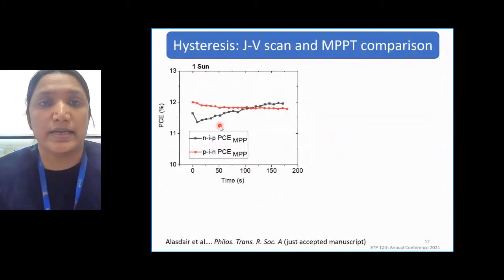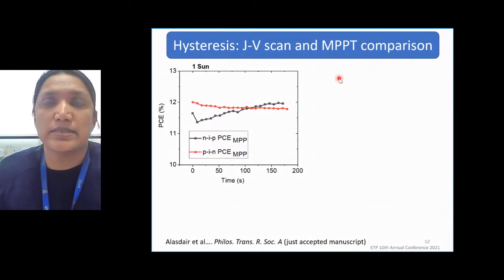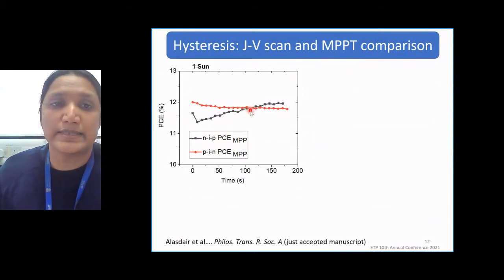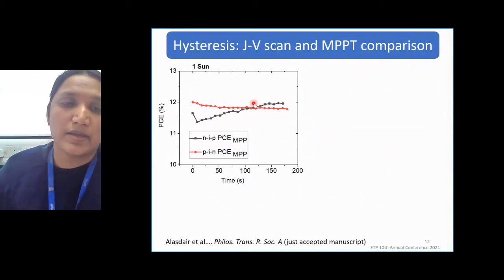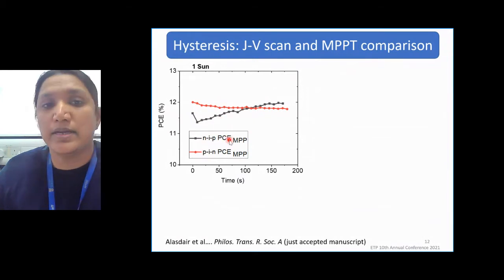We also characterized this hysteresis effect by using the maximum power point tracking method. This efficiency is the most reliable efficiency coming out of a solar photovoltaic device, and it will be the condition under which these photovoltaic devices will be deployed in real applications. Here we can see that from the MPPT measurements, both NIP and PIN efficiencies are quite similar, almost 12%, and similar to what we got from the JV curves. But the main difference is that in the PIN devices, the efficiency stabilizes quite quickly, whereas in the case of NIP devices, the stabilization time taken is quite long. This stabilization time indicates the presence of ionic migration in NIP devices.